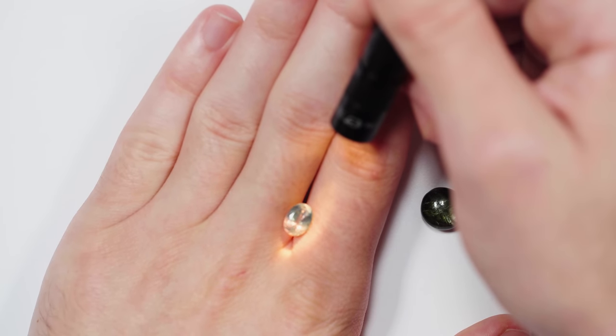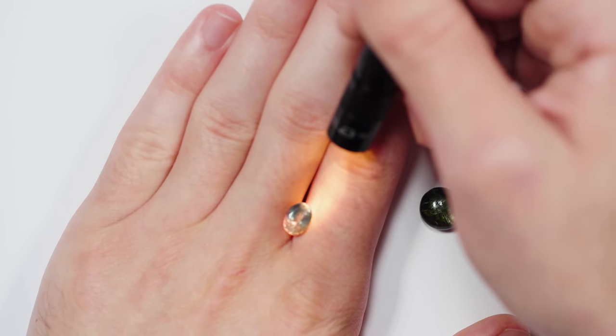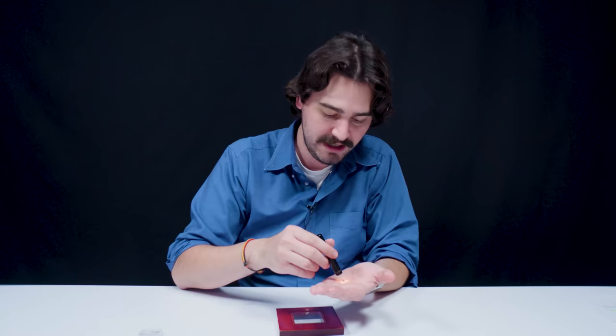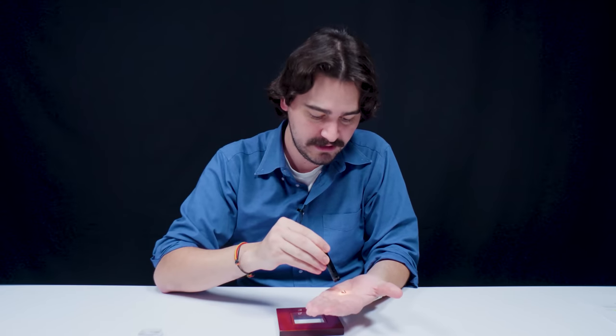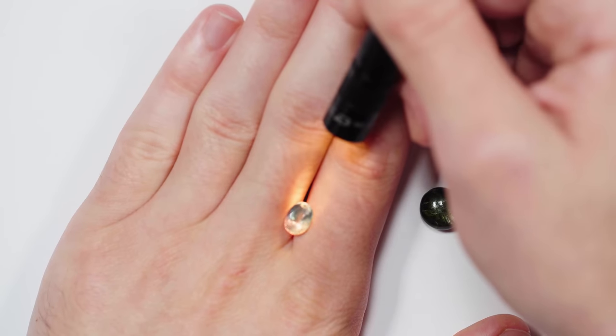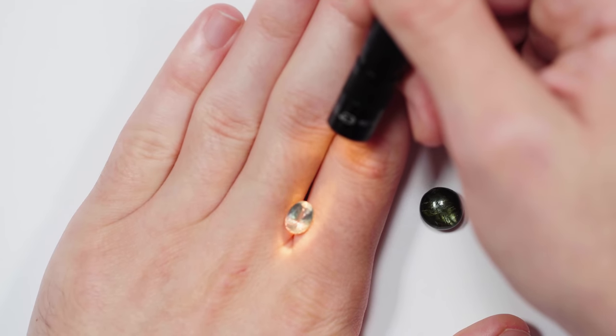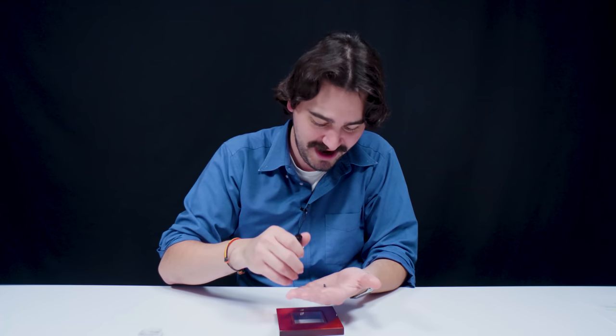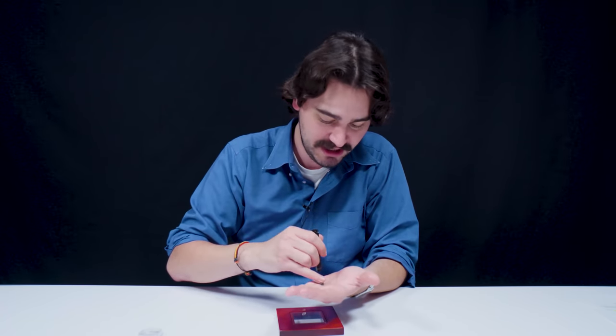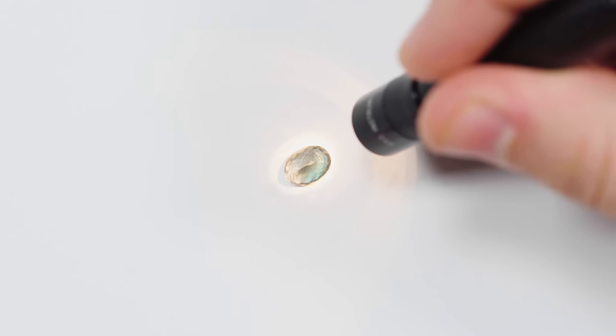That is such a shocking color change. This is an alexandrite. Alexandrite is famous for its color change property. When it's lit with a cool light, like the lights we have here on the set, it appears a nice green color. But if you hit it with a warm light, it immediately changes its color to like a wine red sort of color. I thought when I lit it up that I was seeing my finger through it — that's why it was turning a little pinkish. No, it's turning pinkish because it's alexandrite.